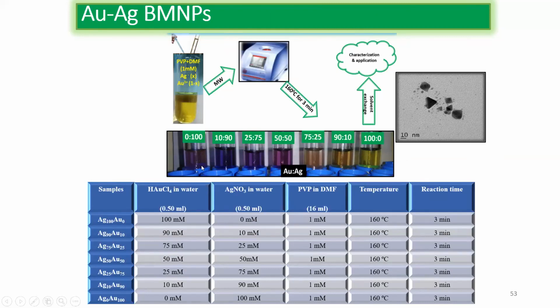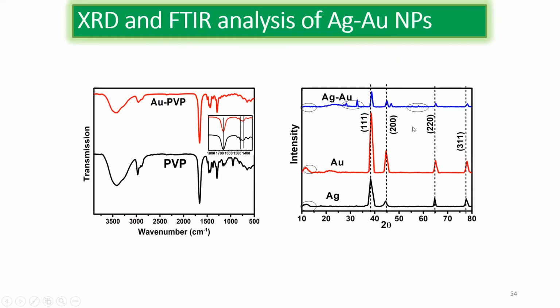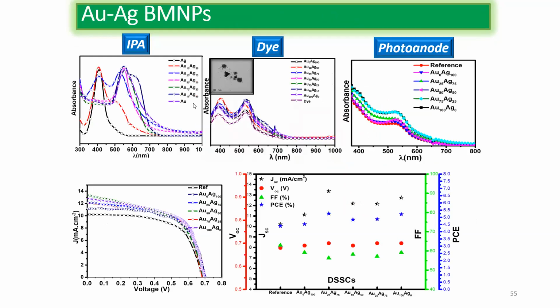And we see that I completely got a polychromatic solution. To check whether the alloy has been formed or not, I did XRD, and we see a little bit of shift in the material, which clearly shows that the alloy has been formed. In the blue one, we can see the peaks of both silver and gold, so I got the characteristics of both silver and gold.